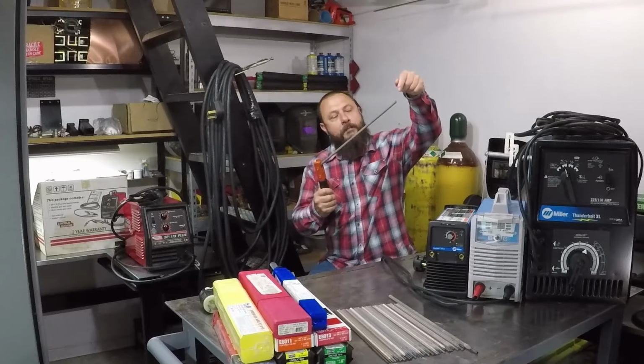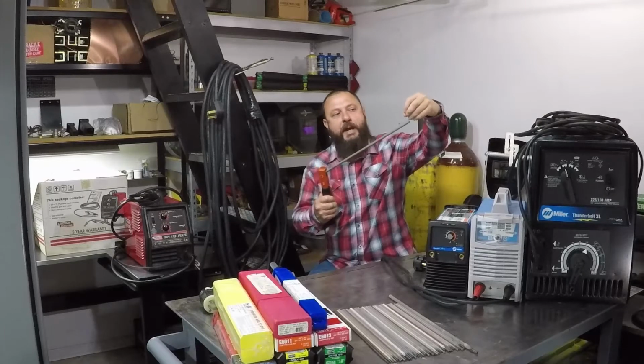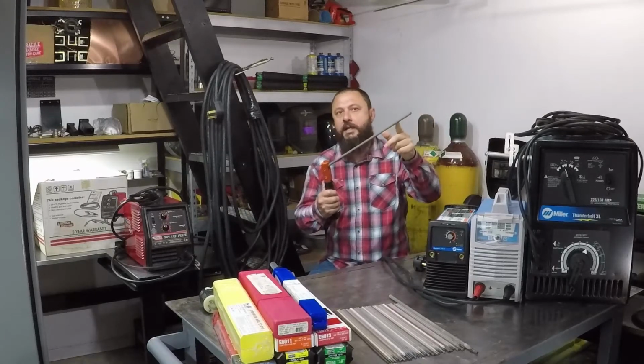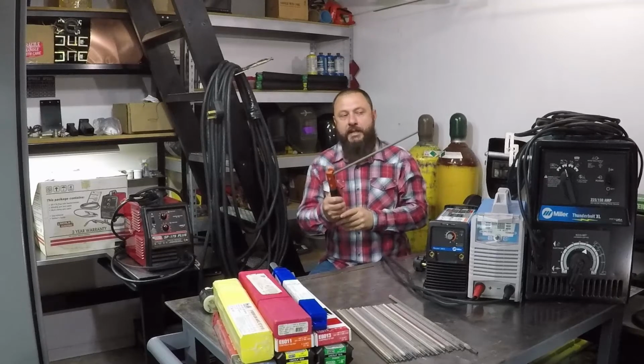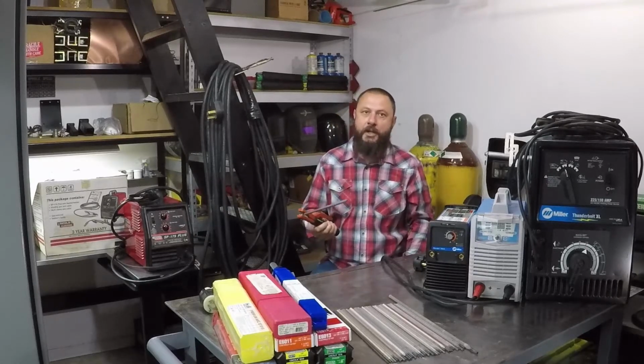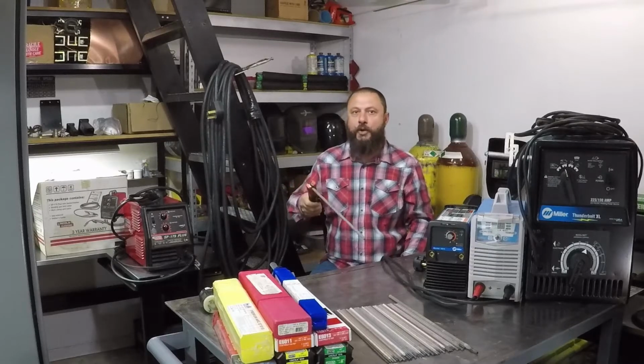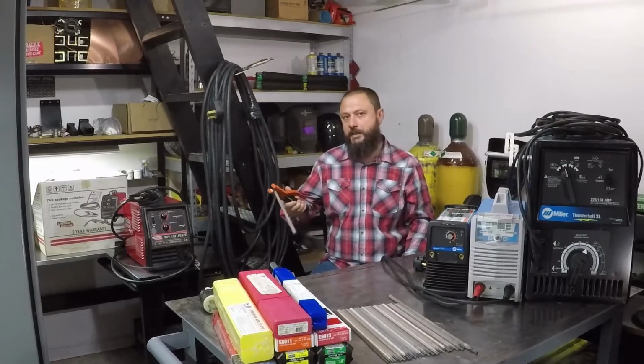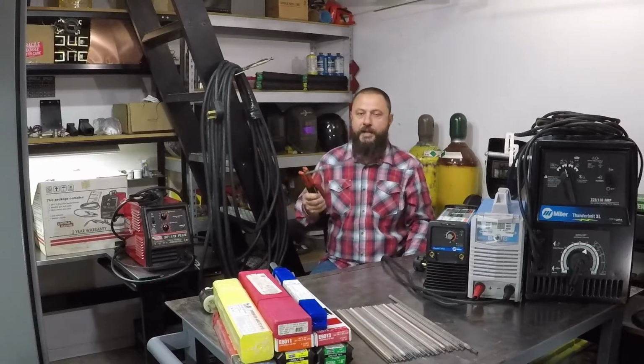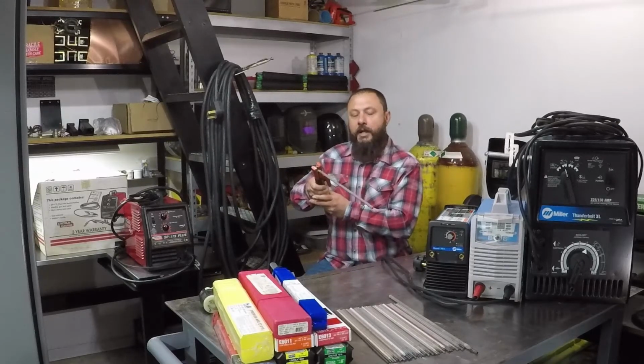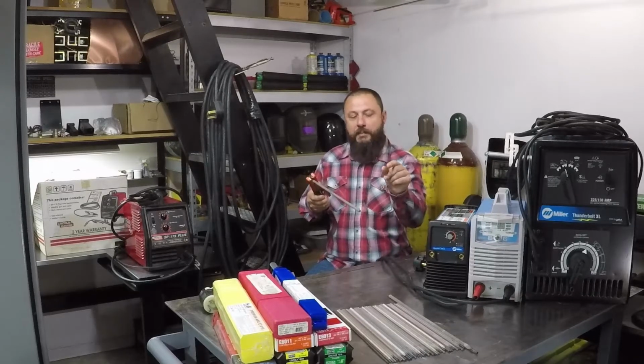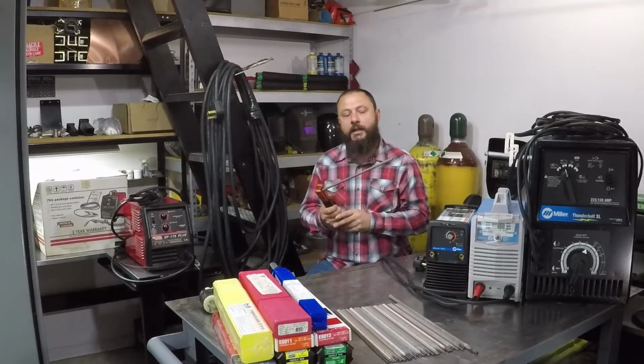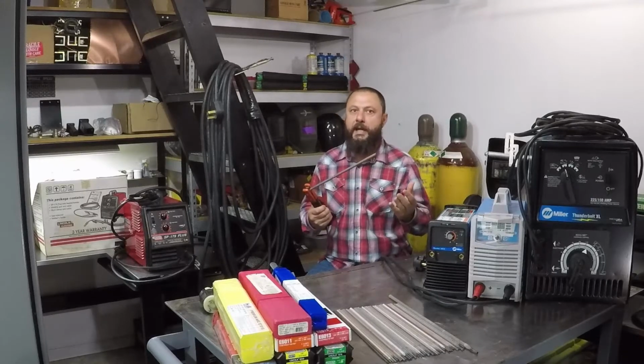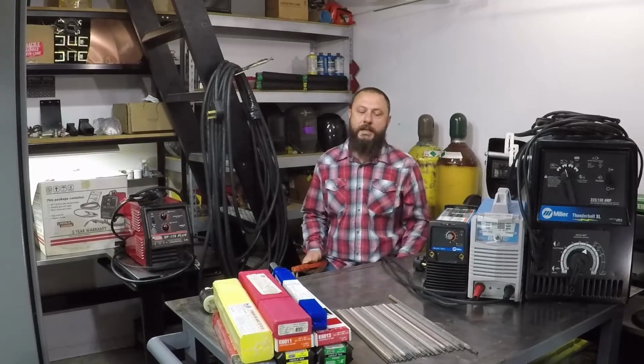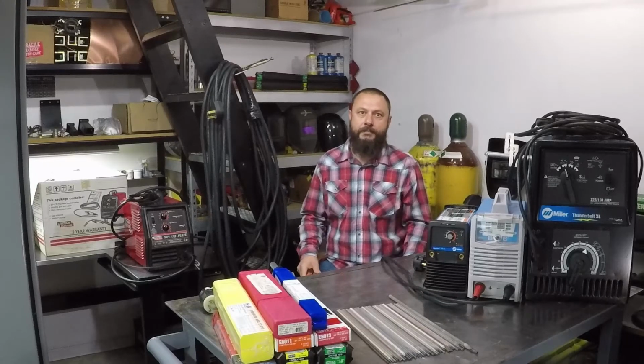will cause the melting metal to come down and then react with the arc and convert to spatter and fly everywhere, and you waste more of the rod fighting that than actually doing the weld. As a general rule, if the rod supports both directions, like 60-10, 60-11 or 80-10, you could weld in both directions. If you weld uphill, the weld will penetrate deeper and the weld may be a little bit thicker. If you're going downhill, the weld may look more aesthetically appealing, however it doesn't penetrate as deep. And that's the difference between both methods.